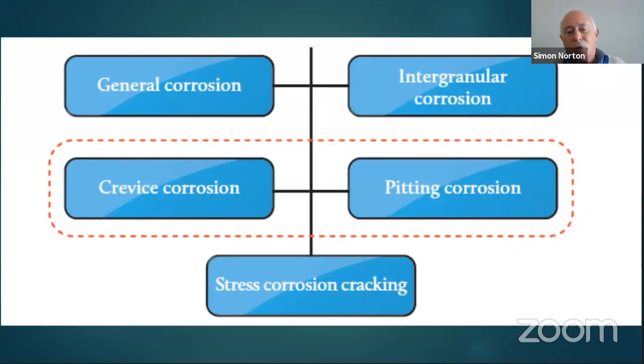So going back to the 5 forms of corrosion that will affect stainless steel. You can have general or uniform corrosion. Yes, that does occur, but you will see that and you can actually measure it. You could put stainless steel coupons into whichever process fluid or application you're going to use, and you can measure weight loss over a period of time, and you can determine the rate at which your stainless steel corrodes uniformly or by general corrosion. But more insidious and dangerous are things such as stress corrosion cracking, crevice corrosion, pitting corrosion, and intergranular corrosion. And I'll touch on those briefly during the case study.